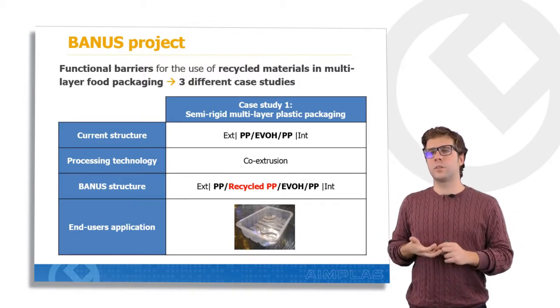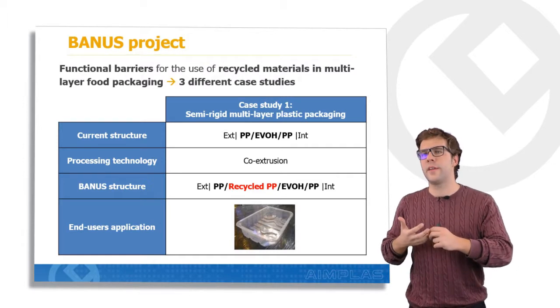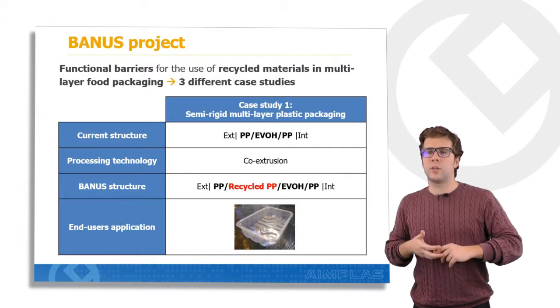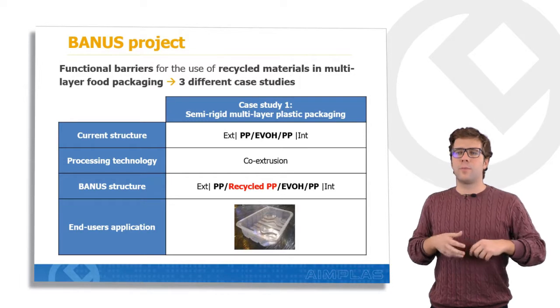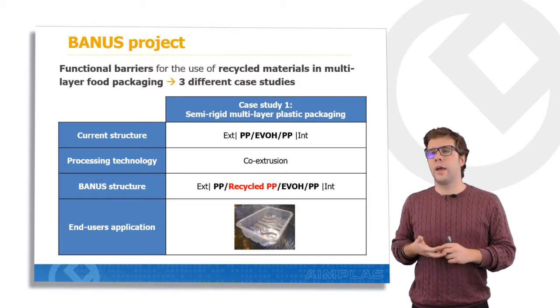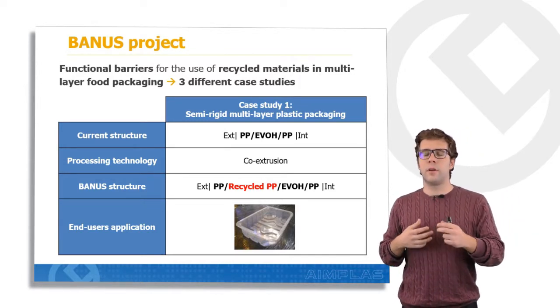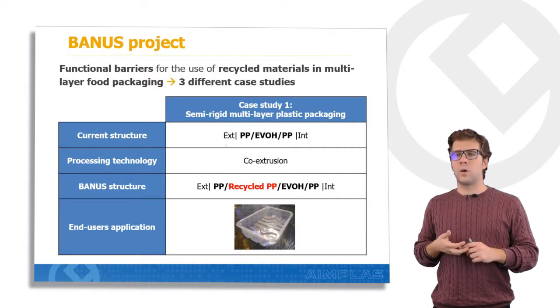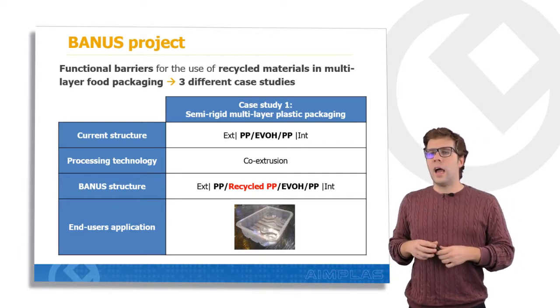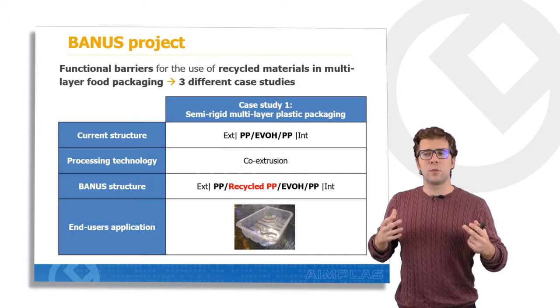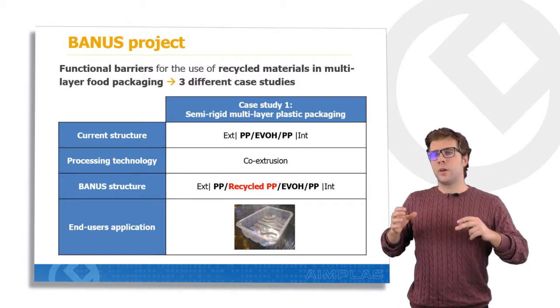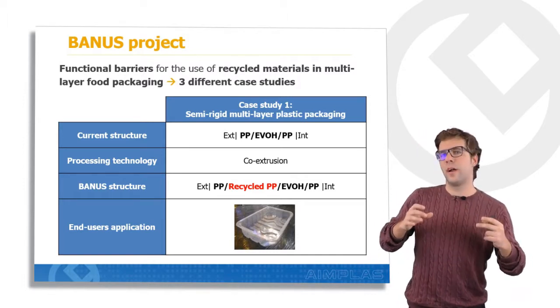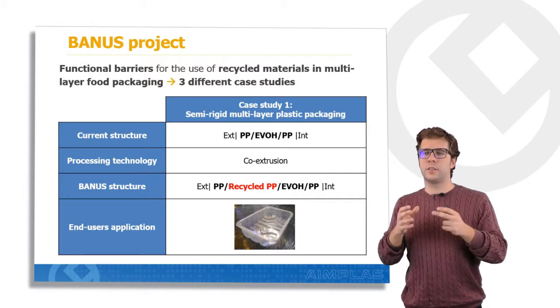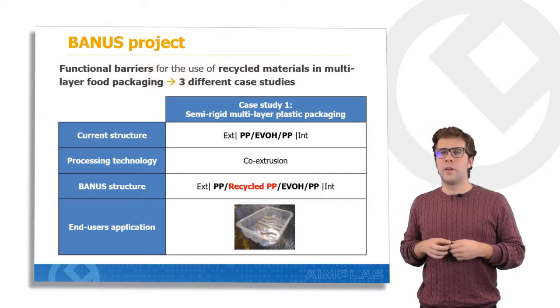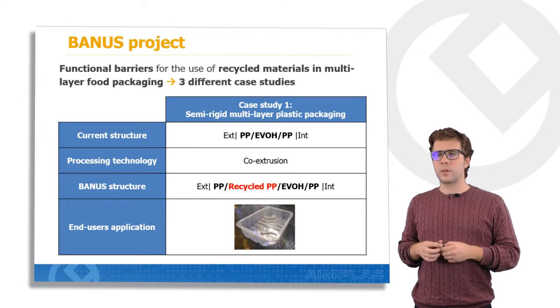The first one was the development of a semi-rigid multi-layer plastic packaging, which was initially made of polypropylene and ethylene vinyl alcohol for improved barrier properties. It was processed by co-extrusion, and in BANUS, what we did was to use polypropylene as functional barrier for recycled polypropylene in this tray for food contact applications.